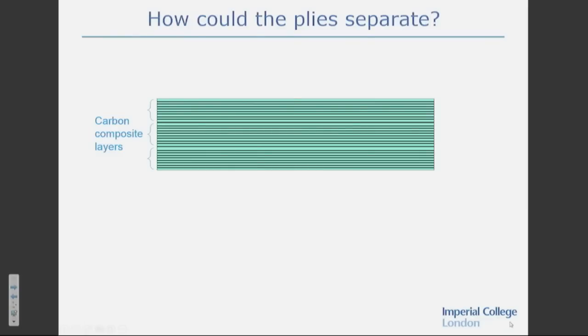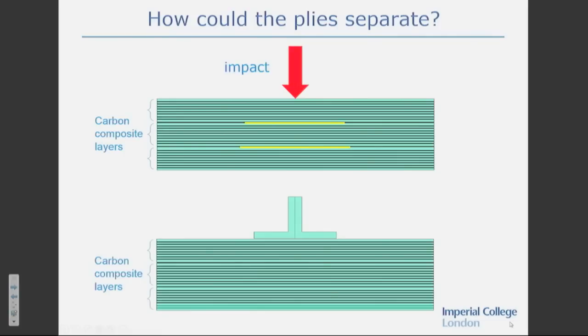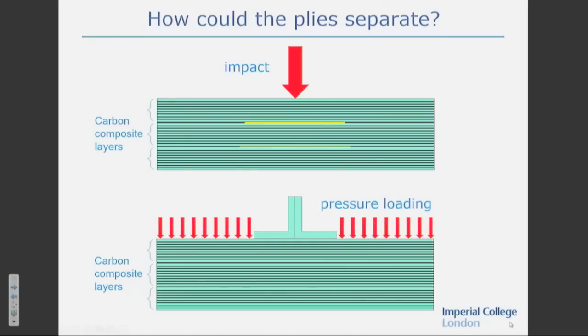How could the plies separate? Well, here's a laminate consisting only of 3 plies. And one of the things that can cause separation is impact. Impact's a great concern for aerospace applications, for example. So we get an impact on the plate, and potentially, if the impact's big enough, we'll get separation at the interfaces here. Here's another example. In this example, we've got the laminate again. It's supported by a T-stiffener here, bonded to the surface. And imagine we've got, say, pressure loading acting on there. Then it's again possible that we will cause failure of the interface between the plies, and we'll have separation of the plies again. And in these cases, I think it's fairly obvious why that loading's causing separation.